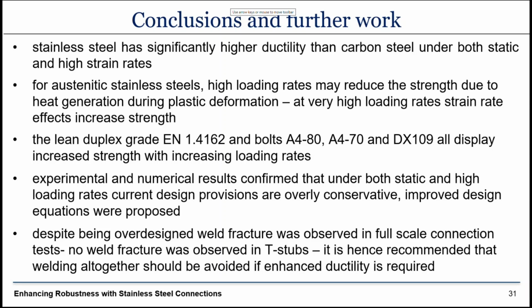The lean duplex grade that originally was not part of the project did not display that strain rate sensitivity. In fact, it became better at higher strain rates. Experimental and numerical results confirmed that under both static and high loading rates, current design provisions are overly conservative, and we suggested some improved design equations in recently submitted papers. And despite over-designing the welds, we did get weld fracture. And our recommendation is that if you have a ductility critical application, avoiding welding would be a good strategy.